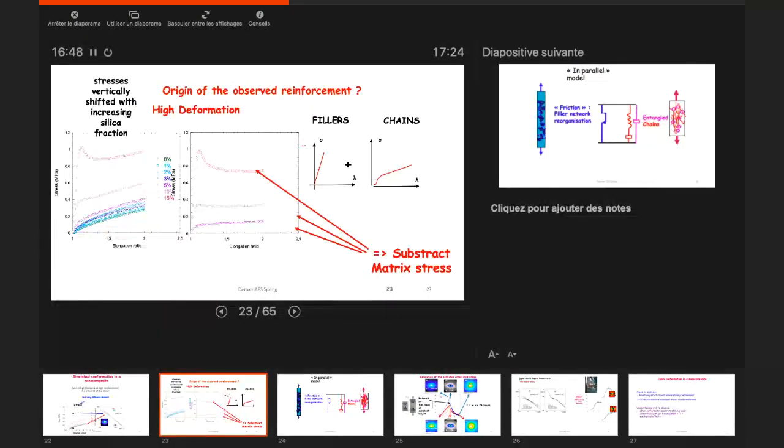The other thing, which we made a statement about, is that the mechanical reinforcement in these systems is basically carried by the particles. Yes, this is what I believe. The statement you made that the matrix chain seems to be irrelevant is completely consistent, but your scattering evidence is different, so mine was just a conjecture. You show that the conformation doesn't change, which is beautiful, because that tells you that everything comes from particle restructuring.